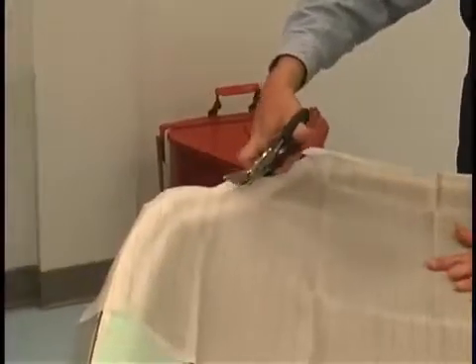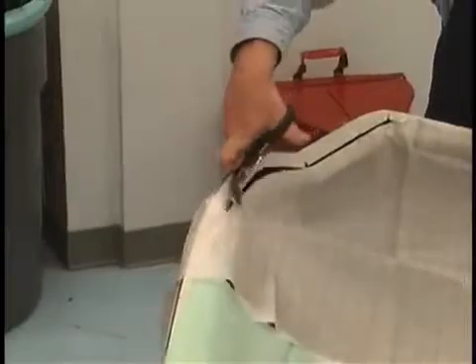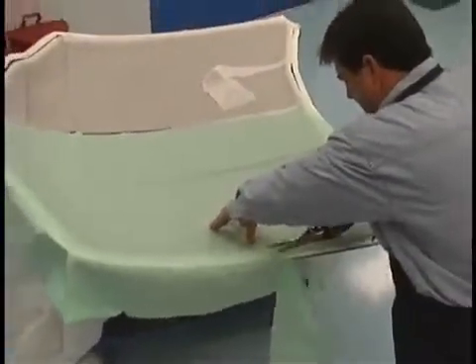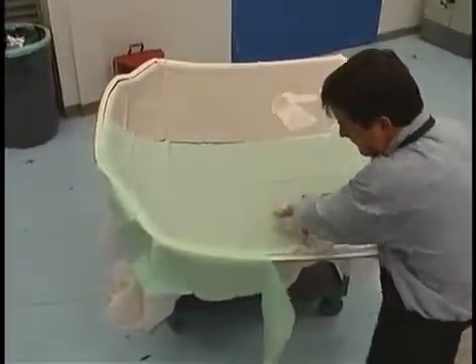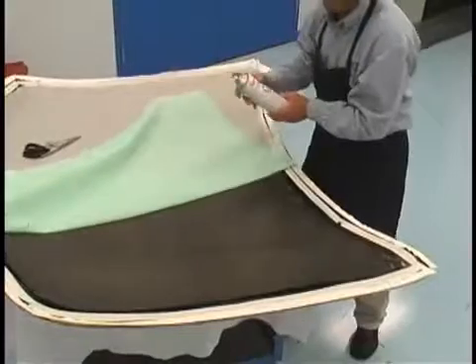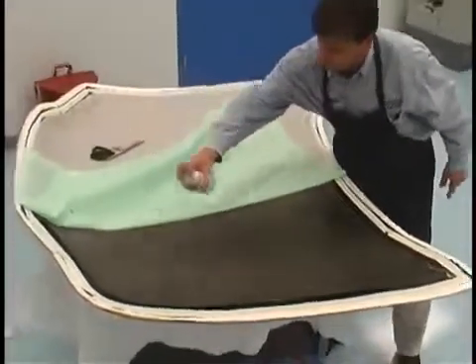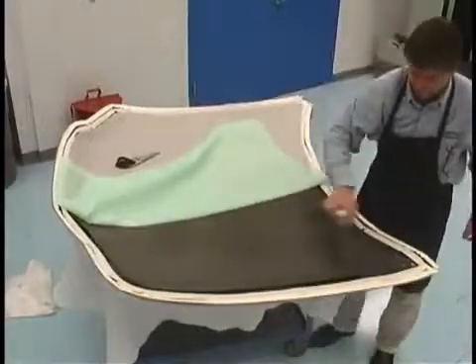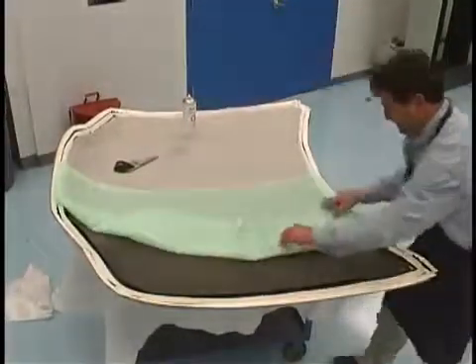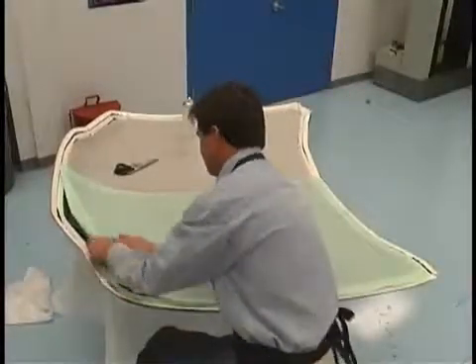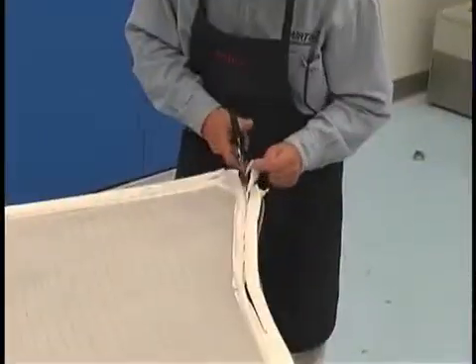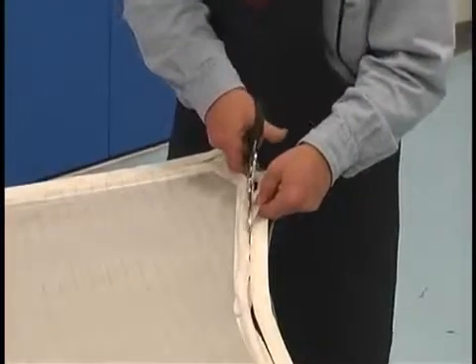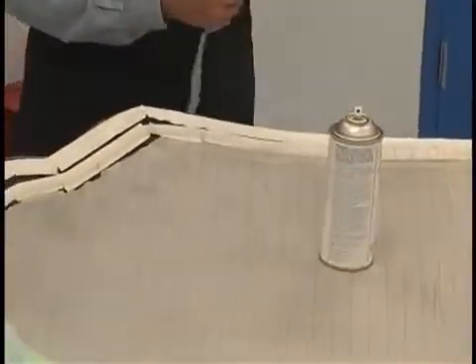However, there is a trade-off. A non-coated peel ply will provide a much better surface for secondary bonding. Spray adhesive is used to stabilize the peel ply to prevent the material from shifting. Strips of peel ply are cut to fit around the spiral wrap. This peel ply is used to provide vacuum continuity between the part fabric and the vacuum channel. These are held in place with AirTac 2 spray adhesive.